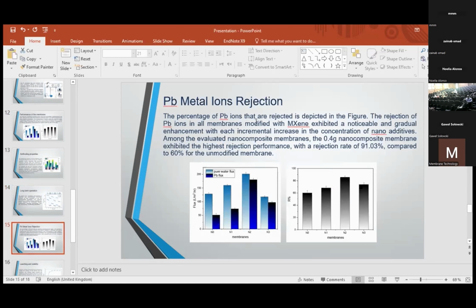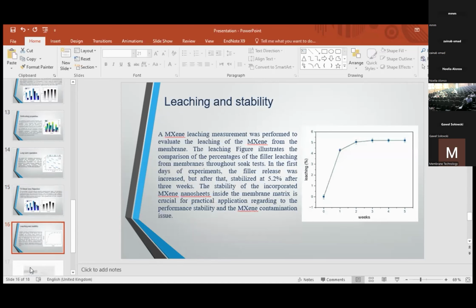The percentage of Pb ions that are rejected is depicted in this figure. The rejection of Pb ions in all membranes modified with MXene exhibited a noticeable and gradual enhancement with each incremental increase in the concentration of additives. Among the evaluated nanocomposite membranes, the 0.4 gram nanocomposite membrane exhibited the highest rejection performance with a rejection rate of 91.03% compared to 60% for the unmodified membrane.